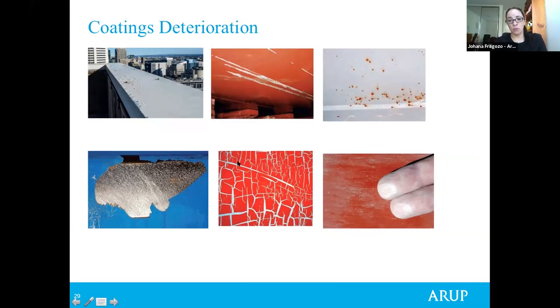There could be some alligatoring, which is probably caused by internal stresses in the coating where the surface shrinks faster than the body of the paint film. And most commonly we see chalking, and this is particularly common with aluminium finishes and stainless steel, coated stainless steel, and it's due to aging of the coating.